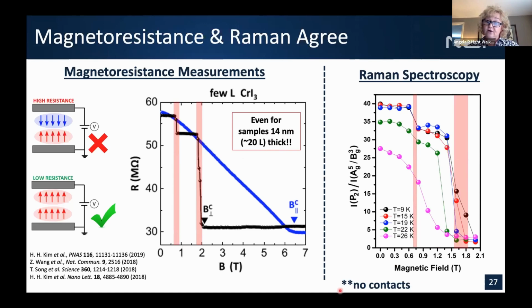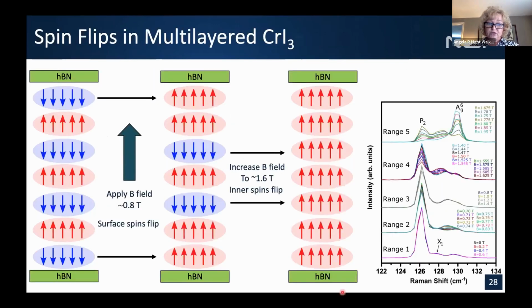What's neat, of course, is that our sample, we believe these measurements are quite intrinsic. There were no contacts put down, no device fabrication, no polymers added, or things of that nature. So what we believe we're seeing with Raman optically is that at 0.6 to 0.8 Tesla, we're seeing the spins flip that are at the surface. They're interacting with the hBN. Again, I mentioned that hBN is both on the bottom and on the top. So at our first major transition, we're seeing surface spin flips. And then as we apply the magnetic field, up to about 1.6, we're able to flip the rest of the layers in this sample.